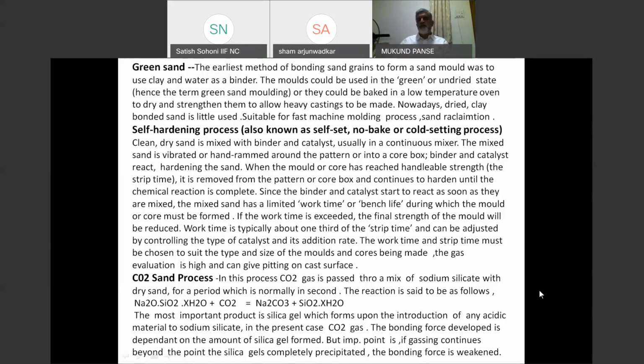The third more important molding mixture used is CO2 sand, where the sand is mixed with sodium silicate and CO2 gas is passed, whereby a silica gel is formed, which subsequently gets hardened. This is also an excellent sand. In fact, it has all the advantages of a no-bake sand, and is much cheaper. Two disadvantages are the gassing time required, and the major disadvantage is retained strength. Its retained strength is very high, and the probability of the casting cracking and difficulty in decoring are both disadvantages.